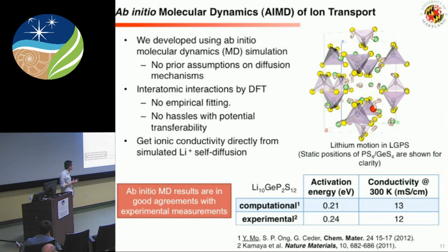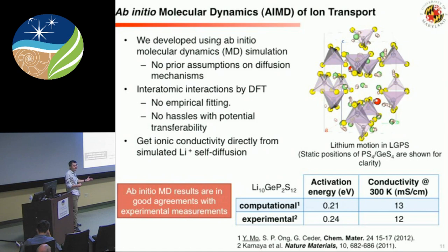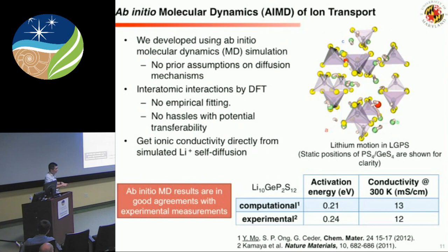So to do that, we developed ab initio molecular dynamics techniques to simulate lithium diffusion in this material. Okay, so we start with the LGPS with the testing. The benefit of doing ab initio molecular dynamics is that usually MD uses some empirical force field. To do it through ab initio, you don't need to worry about empirical fitting. This is actually very critical if you want to design new materials.